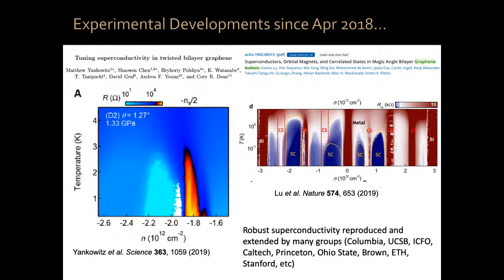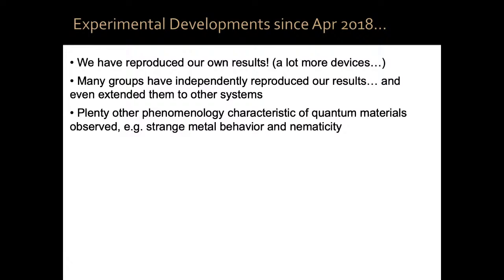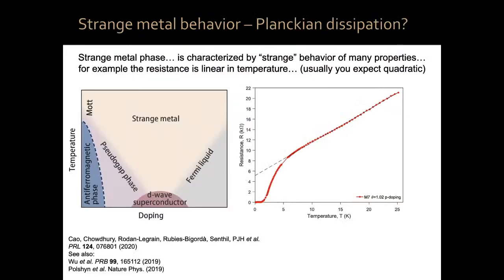And the next thing that happened is that we have measured plenty of other phenomenology which is characteristic of traditional quantum materials, for example, strange metal behavior and nematicity. Let me just mention this strange metal. In this phase diagram of the cuprate superconductors, the biggest wedge is this strange metal. The strange metal phase is characterized by strange behavior, hence the name. Basically, it means we don't know what's going on. But in particular, one of the most characteristic strange behaviors is that the resistivity is linear in temperature at low temperatures when it should be quadratic.